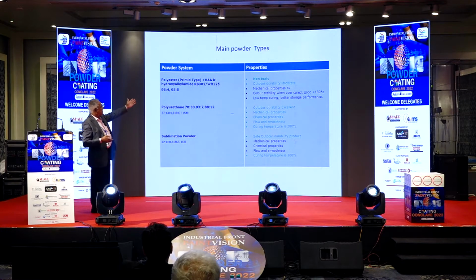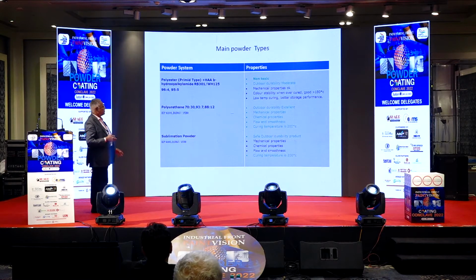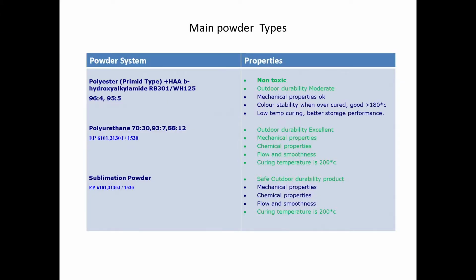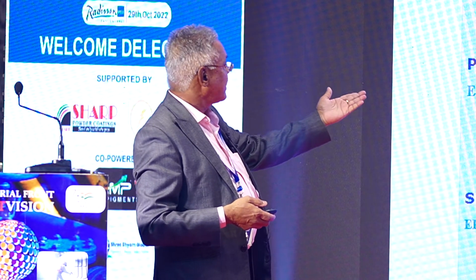The best property in this combination is that it is non-toxic. So almost in Europe and American countries, PP is used with this grade only. Then outdoor durability is moderate. You can use it for outdoor, but for high performance, you have to select a suitable resin for this. In this range, you have to ask for suitable resins. Then all other properties are moderate, and its baking temperature is 180 degree like epoxy or epoxy hybrid system. Then color stability is okay, good, low temperature curing and better performance.